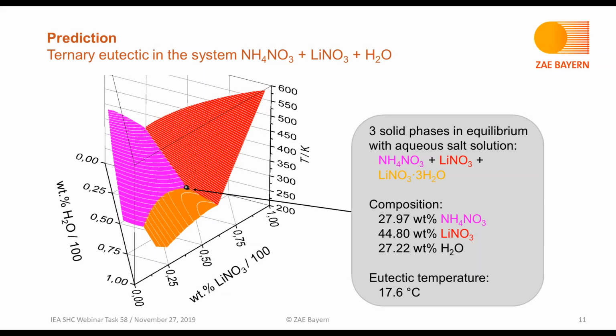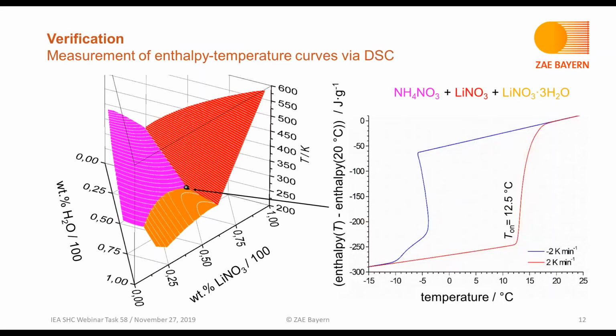And now we are performing calorimetric DSC measurements with a sample of that composition. In this case, it's an example of a successful verification, because what we observe is a single and quite narrow melting transition. This is shown by the red curve. The blue one is upon cooling, the red one is upon heating. So this eutectic is experimentally verified.